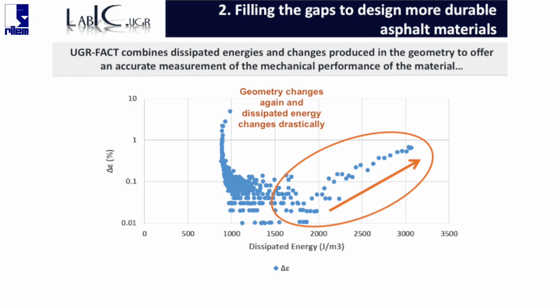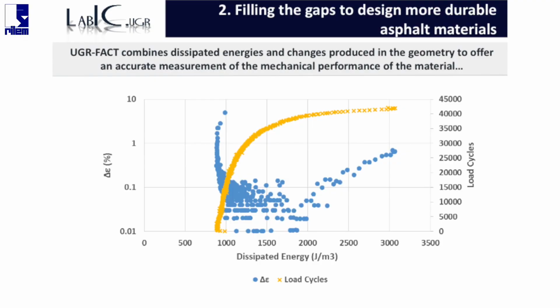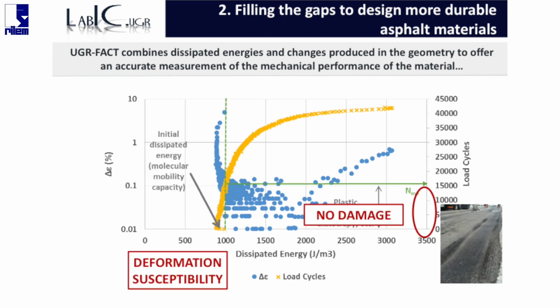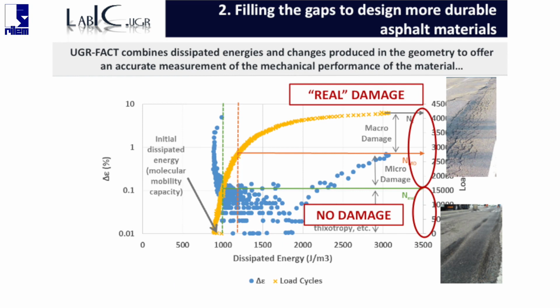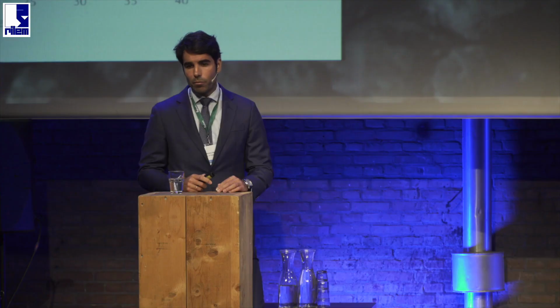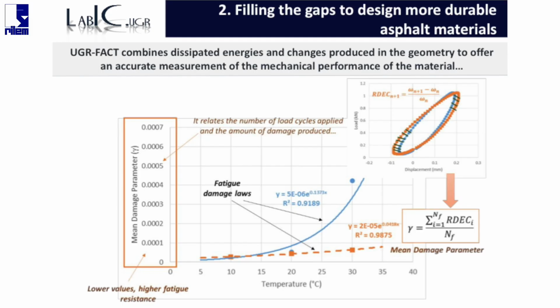If we combine this information with the number of load cycles applied that produce it, we can identify many different properties inside our material. For example, the deformation susceptibility, because we have the number of cycles that does not cause a real damage on my material, just only deformation. But also we can distinguish between the different phases of the propagation of real damage, the micro and the macro process. Taking that information, we can define the mean damage parameter that is a summatory of the increment of the dissipated energy produced in the material during the test, divided by the number of load cycles that need to it.